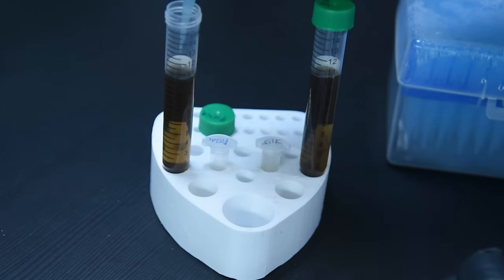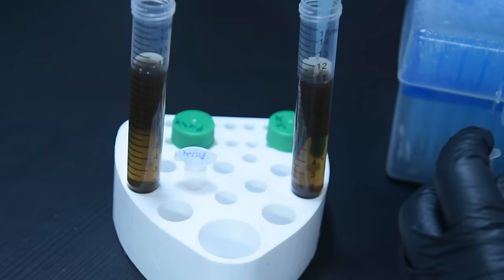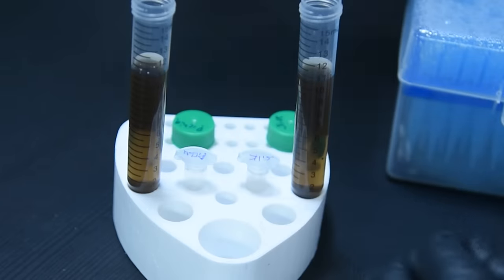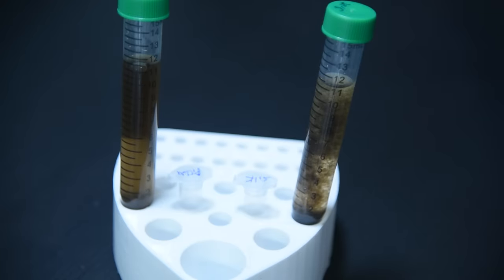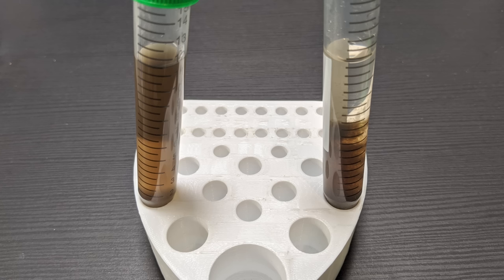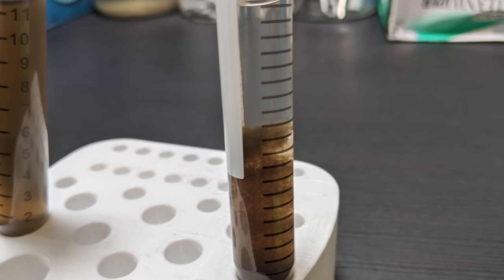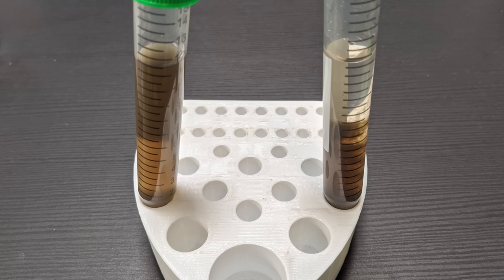It was impossible to see on camera, but the silk solution had an immediate reaction, and it was clear that tiny clumps were forming. I left these to sit for a few minutes, and when I came back, the silk tube had coagulated nicely. And after about an hour, the coagulated mass of silky graphene had mostly sunk in the tube, leaving a water-clear, graphene-free solution above it, while the plain yeast looked exactly the same as it did at the start of the test.